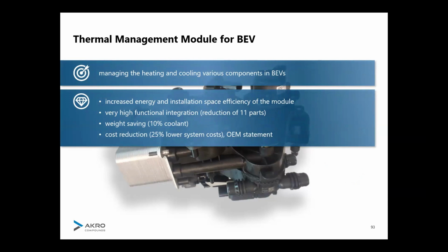And the weight saving, and that is interesting, is not only coming from reducing parts and making it smaller. If you look at the whole system in your car, of course, if you have fewer components, you have fewer tubes in between, and you need less cooling agent in your whole system. So when looking at the weight saving of just the part, we talk about roughly 30% saving, but on top, you could eliminate 10% of the cooling agent in your system. I don't know the numbers, but imagine you had 5 liters before, and then you have only 4.5 liters left. You already save 500 grams of just cooling agent.